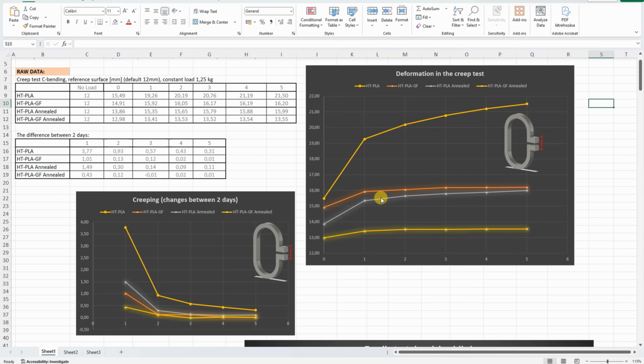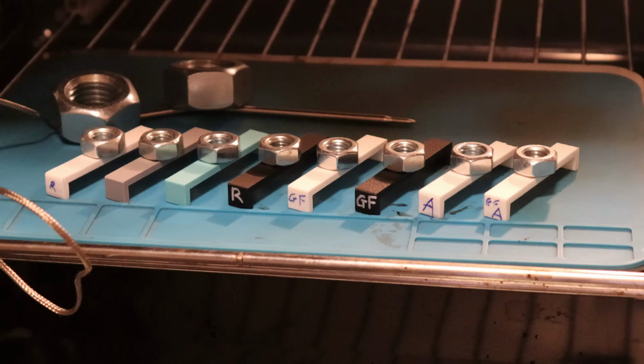And the difference between 2 days we can see on this graph, that's the creeping, and we can see only HT-PLA had some creeping even on the 5th day, and this is very typical for average PLA materials. All three are very good in this test, and basically they stop with the deformation after day 2. This is very minimal. Temperature test in the oven, and I need this for my documentation too.